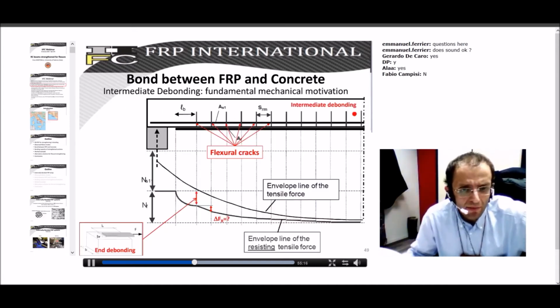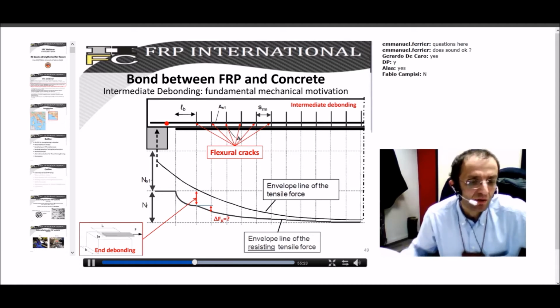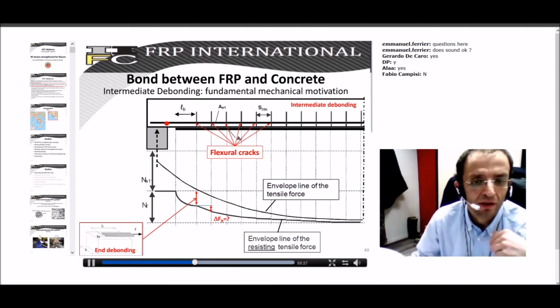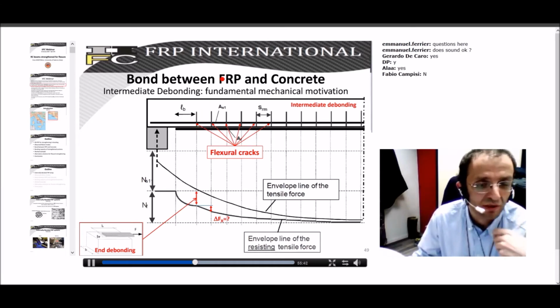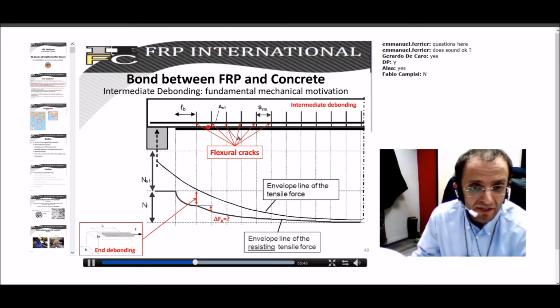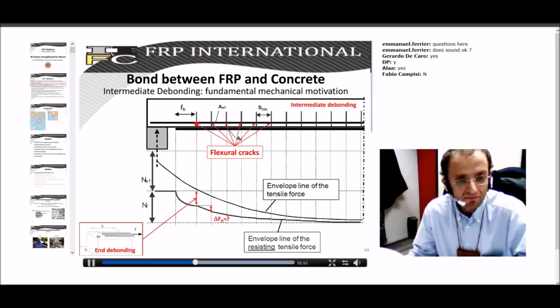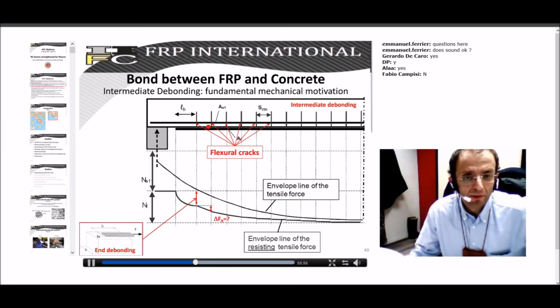Actually, we have our beam. As a matter of principle, we can figure out a possible mechanical explanation for the occurrence of the intermediate debonding, because between these two cracks, depending on the applied load, we can evaluate the delta sigma, the actual increase in axial stresses due to the applied forces, and we have to compare this increase in the axial stresses between this section and the other section. We have to compare this increase with the maximum delta sigma which can be borne, which can be accepted, between these two sections.